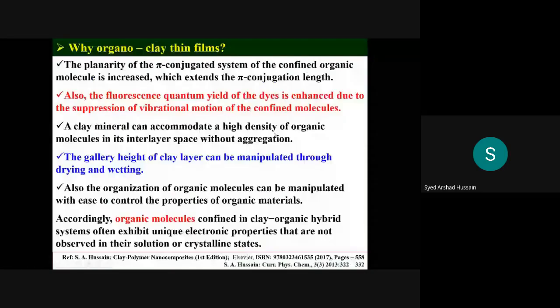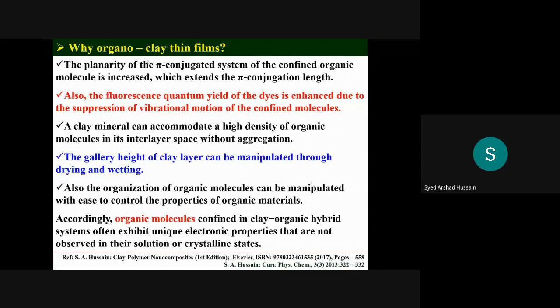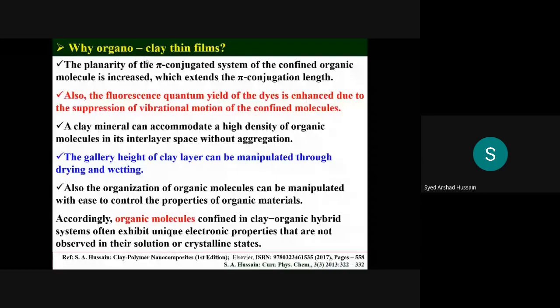Now, why these organoclay thin films? The planarity of the pi conjugated systems of the confined organic molecule is increased when you incorporate them in between the clay layers or on the surface. That means it extends the pi conjugation length. Also, the fluorescence quantum yield of the dyes is enhanced when you incorporate them in between the clay layers. Why? Because you can suppress the vibrational motion by confining them within the clay layers. So these two properties mainly help you to manipulate the optical behavior or electronic behavior of your dyes incorporated in such systems.